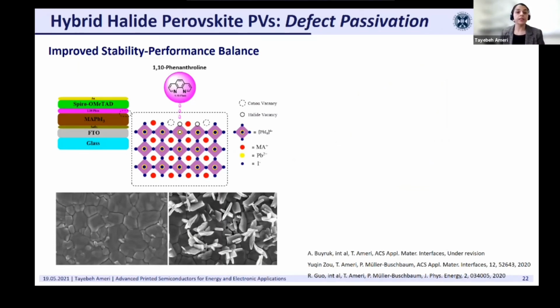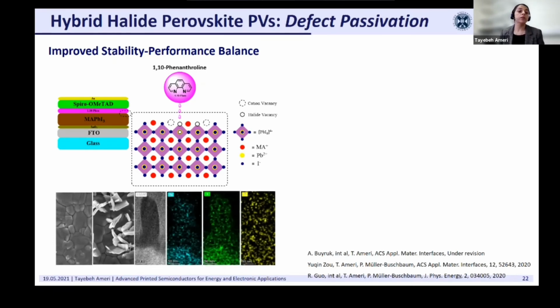One of them here as an example is this 1,10-phenanthroline, that you can see when we introduce it on the surface of our perovskite solar cell. We are completely changing the surface, and new platelets form on this surface. Our highly sensitive TEM characterization, actually analytical characterization, showed that what is formed on the surface has a completely different nature than a pure perovskite or a pure small molecule.